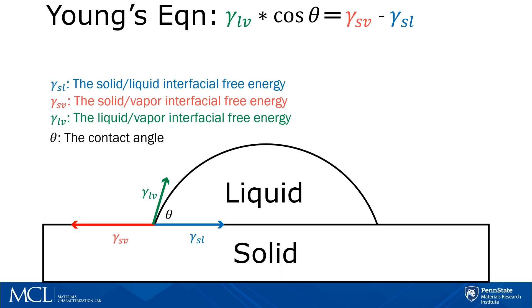The work resulted in the equation listed above, showing that the contact angle between a solid and a liquid is governed by the interfacial free energies between those three phases. This was a wonderful generalized relationship for surface energy, but as we can see, there are four terms in the equation. Measuring the contact angle removes one of those, but there are still three terms that must be accounted for. This means that some prior knowledge of the system is required to obtain surface energy measurements with this method.